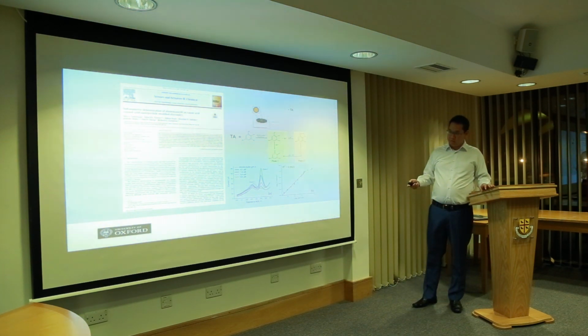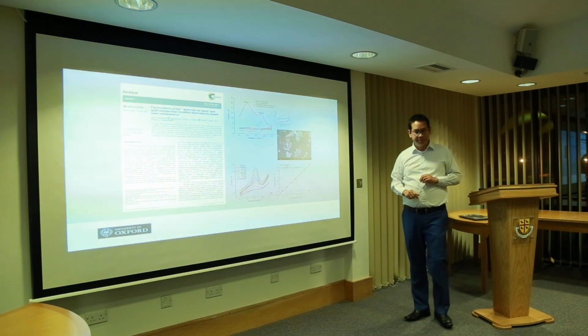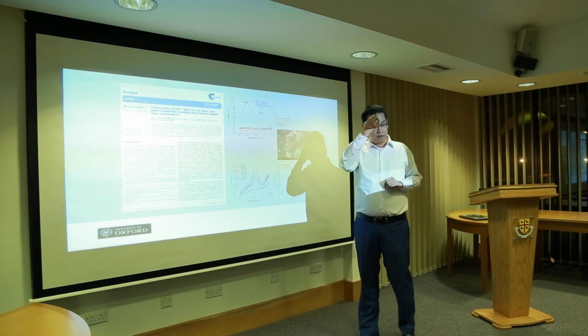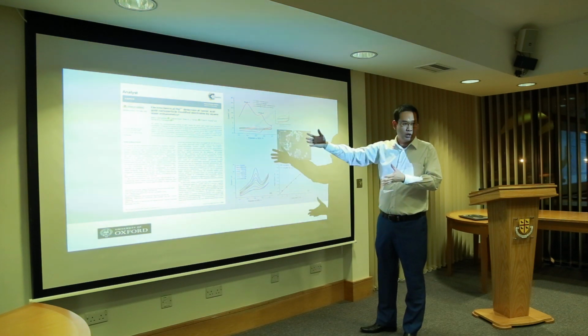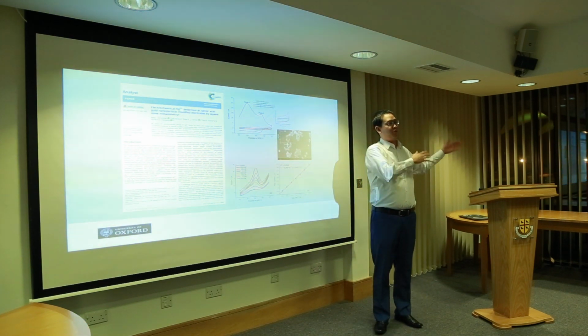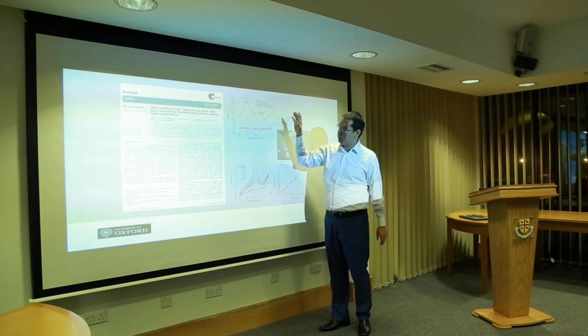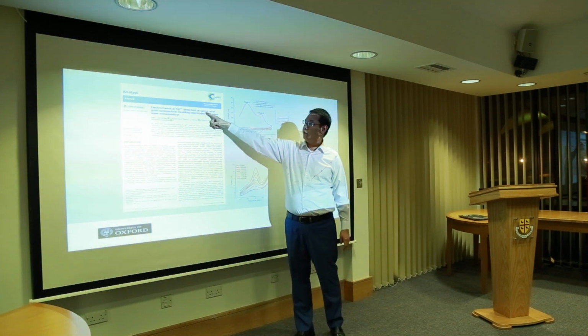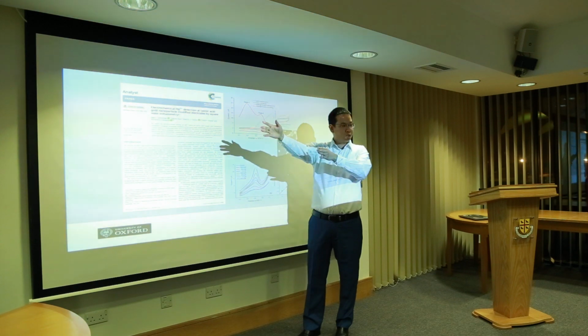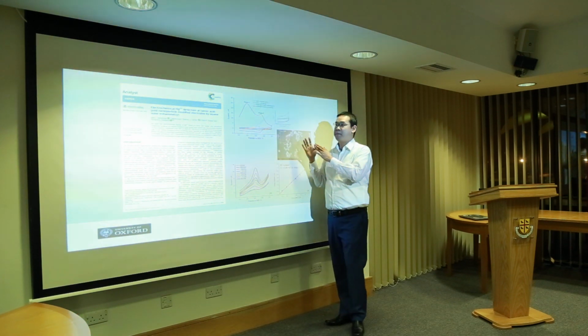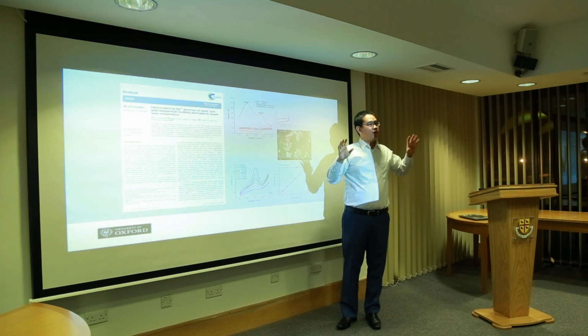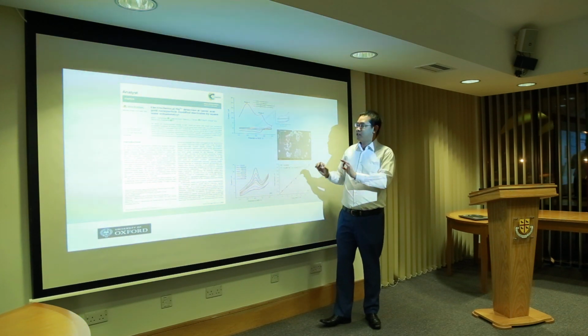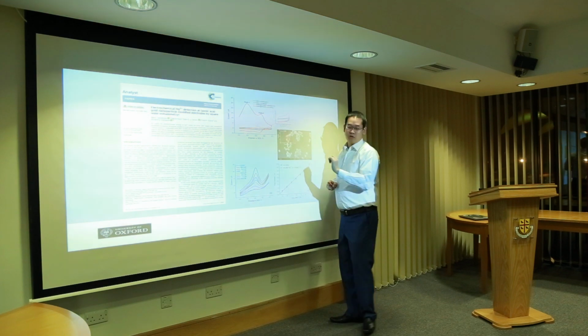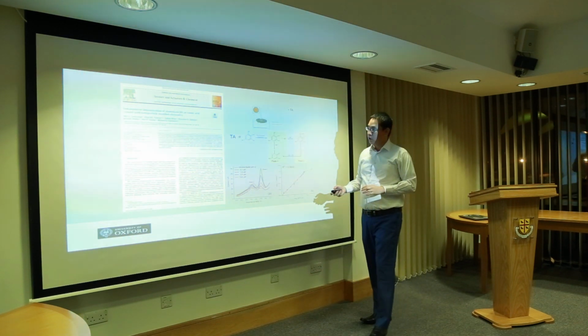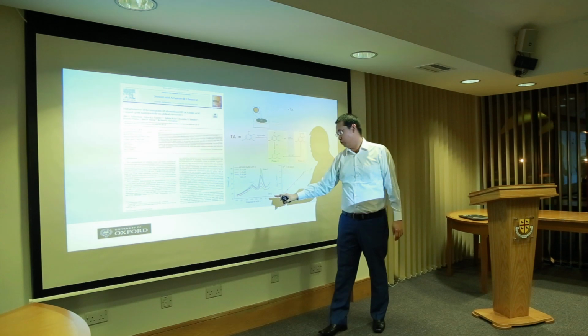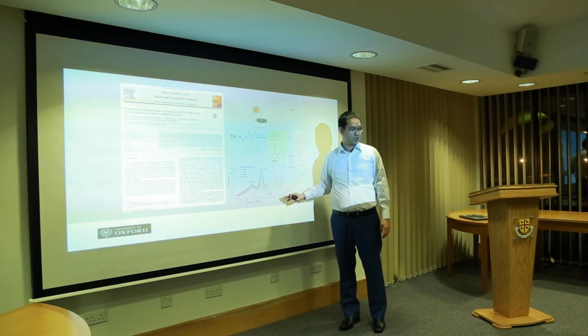Another voltammetric technique, my fourth paper, during my DPhil, we also wanted to detect mercury in the same system. So what's the difference from the previous one? We have the same material, gold nanoparticles capped with tannic acid, but the first one detects aluminum and the second one mercury. It's a very unique system because when you apply a specific starting potential, for example this one, you start from 0 to 0.7 for the oxidation process.